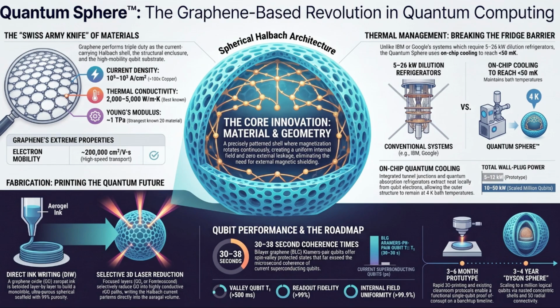The Quantum Sphere white paper proposes throwing away the flat silicon wafer entirely and relying on graphene. Now, we've all heard the hype about graphene for years. It's a single layer of carbon atoms arranged in a hexagonal lattice, like chicken wire. Right. But the statistics listed in this paper frankly look like typos to me. Let me just share these numbers with you. The current density, which is how much electricity you can push through a given area, is 10^8 to 10^9 amps per square centimeter. It's massive. The paper notes that is more than 100 times better than copper. It is. If you tried to push that much current through a microscopic copper wire, the copper would instantly vaporize from the heat. Graphene just handles it effortlessly.